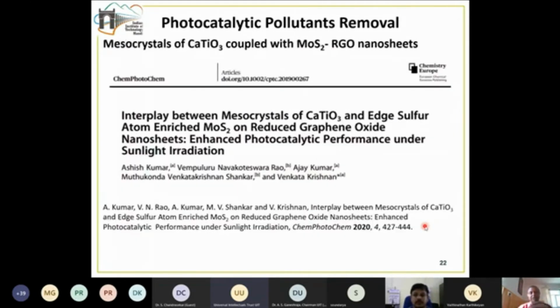And in yet another work, we thought, can we make a material which is good both for photocatalytic hydrogen evolution as well as for photocatalytic pollutant removal? So we took calcium titanate and made mesocrystals of it. Mesocrystals means they have small crystallites, like small ice cubes, which are kept together. Then we coupled this mesocrystalline calcium titanate with sulfur-enriched, defect-rich MoS2 and reduced graphene oxide. We studied its photocatalytic performance for both hydrogen evolution and pollutant degradation, and we got very good results. These results were published in the journal ChemPhotoChem in 2020.